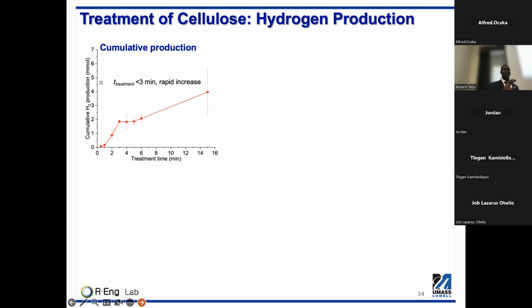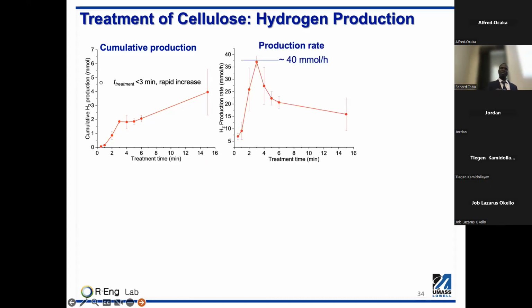Now, we also look at the hydrogen production for cellulose and low density polyethylene using this spark dielectric barrier discharge. We considered four different parameters. One of them is the cumulative hydrogen production. This is the cumulative hydrogen production for cellulose, which increases more rapidly within the first 3 minutes and then increases steadily. For the hydrogen production rate, we see that it increases rapidly up to a maximum of 40 and then starts declining a little bit.